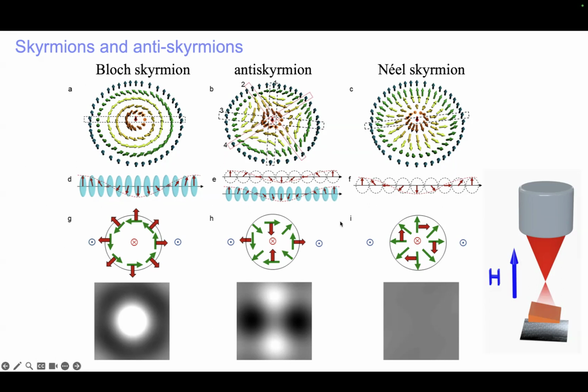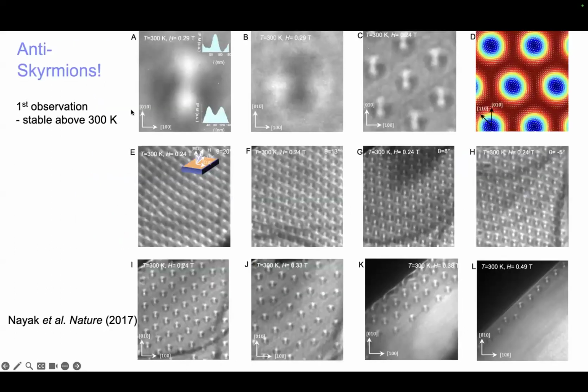And for an antiskyrmion, we calculated we would expect to see this clover leaf-like structure, two white regions of increased electron intensity and two black regions of decreased. And that's actually what we saw on the top left. We saw an antiskyrmion for the first time in a complex Heusler compound, which had the appropriate symmetry that was predicted to display this antiskyrmion.